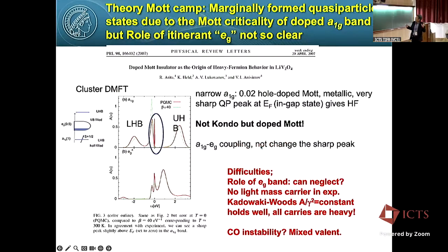However, I was a bit curious whether we can neglect the role of the eg band. Because if the eg band contributes, we should see some contribution from light mass carriers, right? But since we saw this Kadowaki-Woods relationship for T-square resistivity very well, that means all carriers are kind of heavy. And that's one point. Also, because of mixed valence, like magnetite, we do expect charge ordering instability rather than quantum criticality. So those are my question marks.